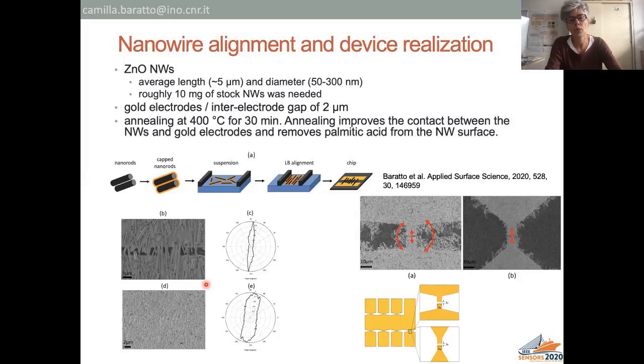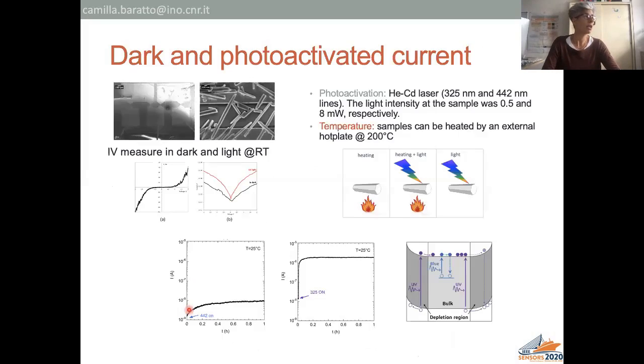The presence of broken nanowires reduces the degree of alignment. Like in this case, you have a worse degree of alignment between the electrodes. So it's important to avoid having debris. And the current that we can obtain from this type of alignment, where just a few long nanowires are contacting the two electrodes, is in the range of nanoampere, and the curve is symmetric. The current can be increased by shining UV light over the sample.